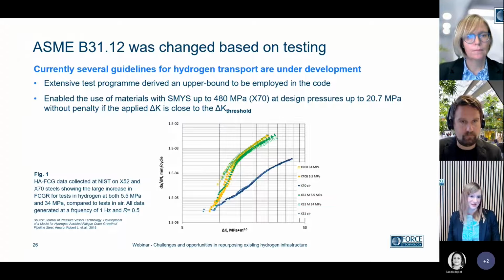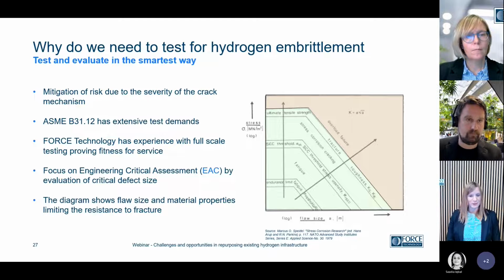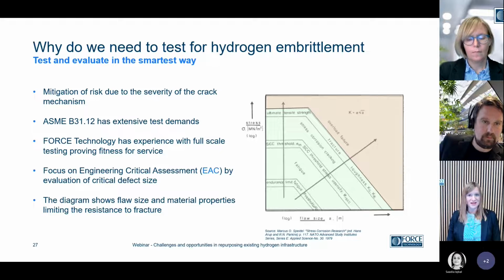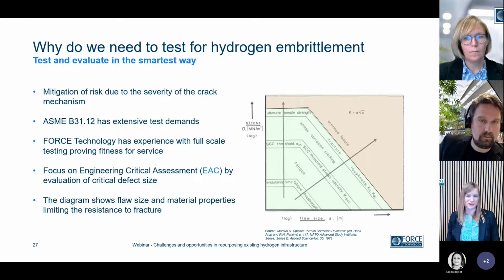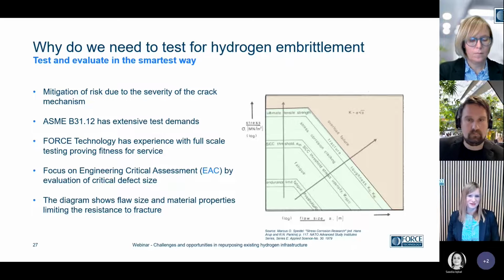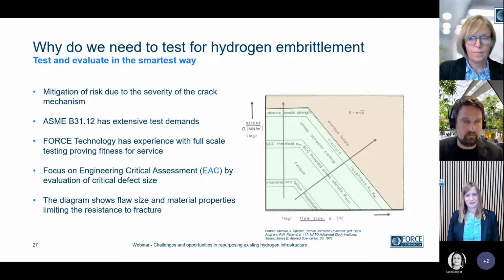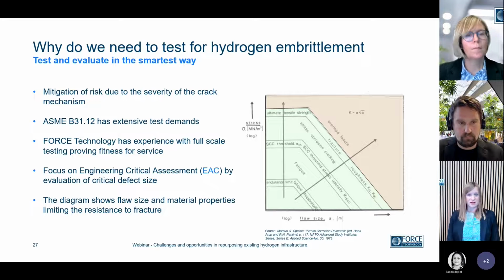So testing is needed, and this is just an example of how ASME was changed based on testing. So it allowed the use of X70 steels at higher design pressures. But tests should be targeted. And for repurposing, the ASME B31.12 demands a huge test scope. We believe that targeted testing would be smarter based on review of a specific pipeline section, knowing where the defects are and of what size. And this use of a holistic approach and engineering critical assessment of defects, taking this into account would provide a more sound evaluation of the actual condition for repurposing.